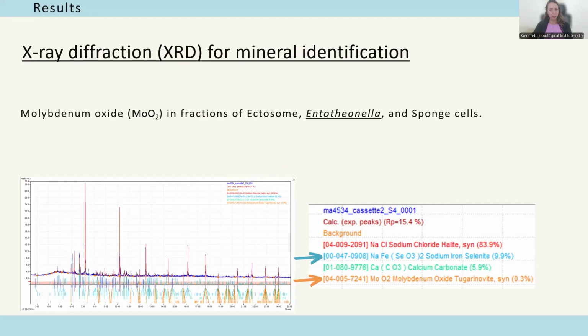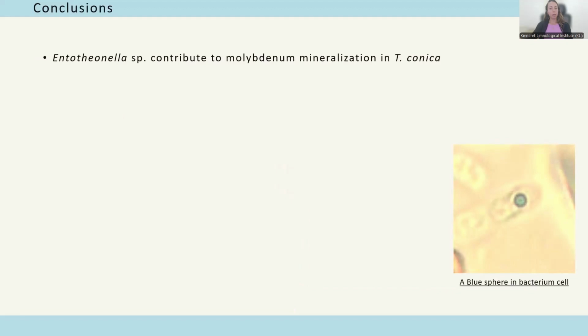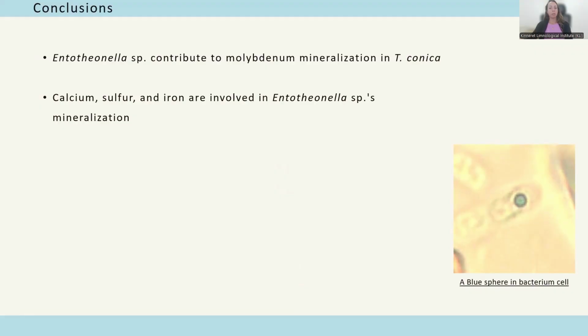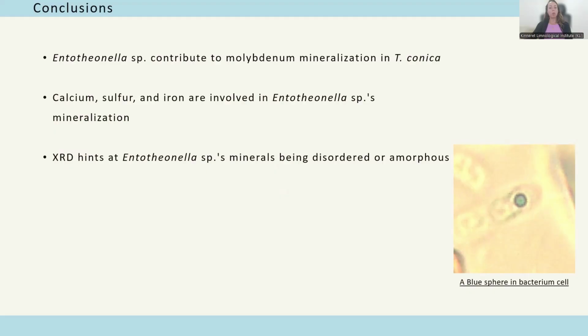For a material science audience, this is an important open point. Future work should combine higher resolution structure analysis, oxidation state analysis, and targeted isolation of these spheres. I will now summarize the biological interpretation. The combined evidence suggests that Entotheonella contributes to molybdenum mineralization or sequestration in Theonella conica. The strong evidence comes from the intracellular molybdenum-rich spheres observed by TEM-EDS. Calcium, sulfur, and iron were also present in these spheres, suggesting that these elements may participate in the mineralization process, and the lack of a clear crystalline signal from the intracellular spheres suggests that the material may be disordered or amorphous.